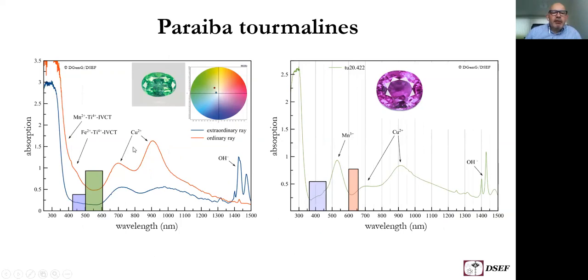These are absorption spectra for green Paraiba tourmalines with, again, the 2 copper bands with iron-titanium charge transfer and manganese-titanium charge transfer, leaving behind a transmission maximum in the green and in the blue area of the visible spectrum. And on the right, there is a non-polarized spectrum of a purple copper-bearing tourmaline.